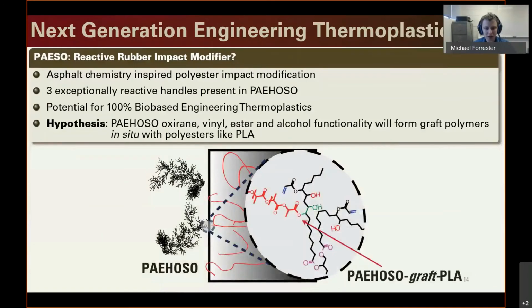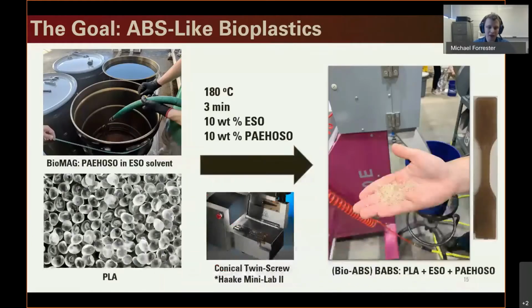But we had this thought, if we can take our PAESO system and incorporate it into the PLA using some of those functional groups, can we form some in situ grafts of PLA and PAESO to make something that has very high strength and end up making something that is ABS-like plastic. ABS, acrylonitrile butadiene styrene, is one of the most useful engineering thermoplastics in the industry, but there's a huge push to move away from purely petrochemical non-compostable polymers.